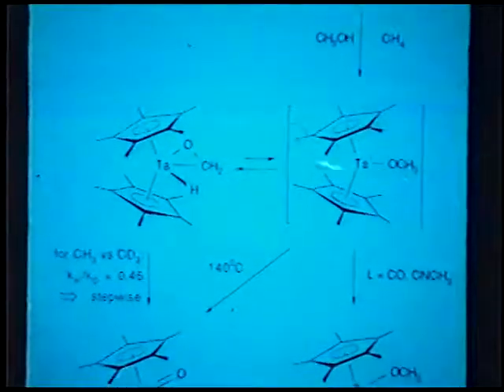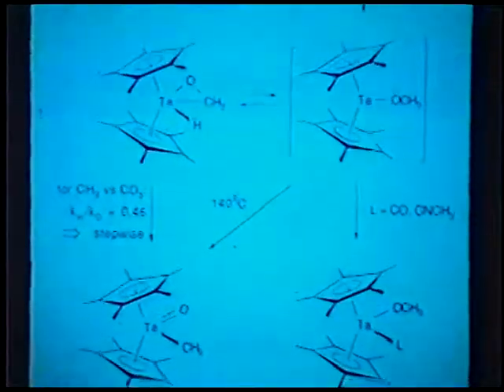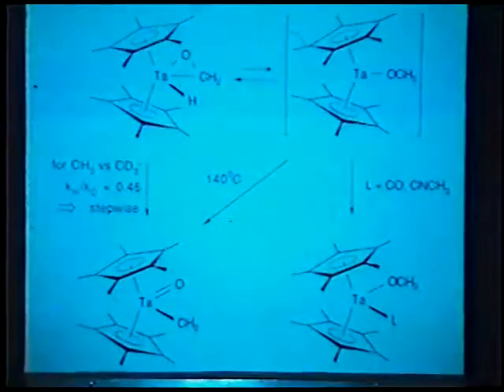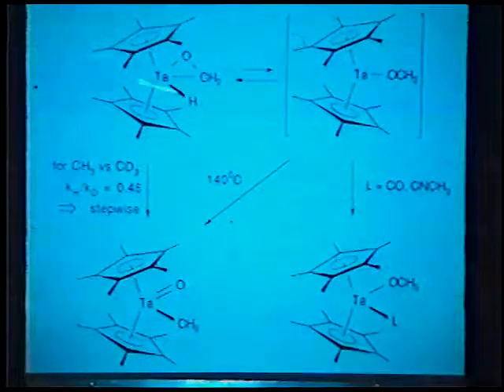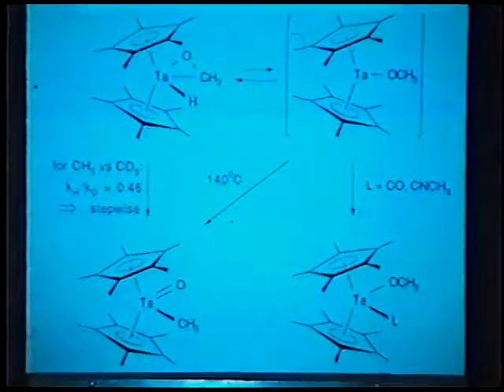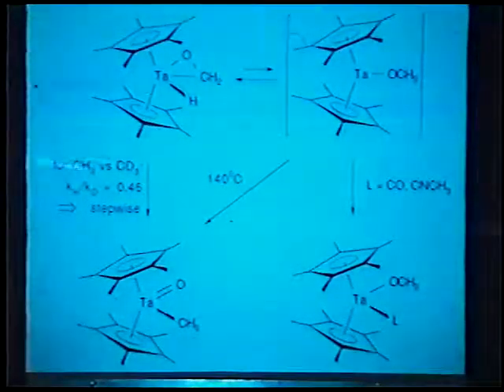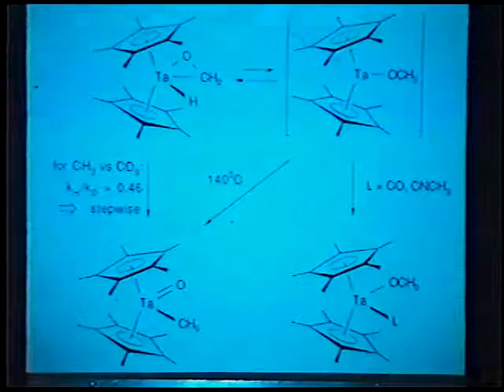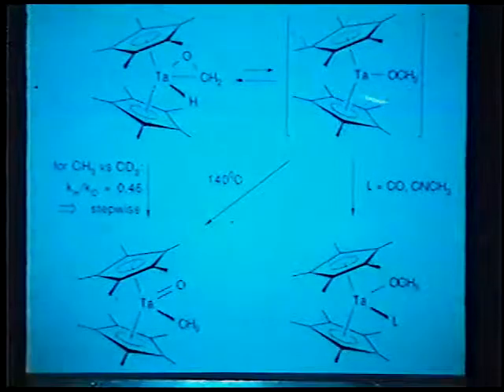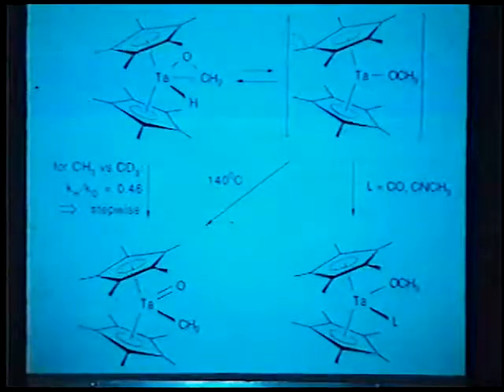With methanol, we get very clean transformations that involve loss of methane from the methylene hydride and formation initially of this formaldehyde hydride derivative of tantalum. This is reversible. You can show that by dynamic NMR techniques and also by trapping the methoxide with simple ligands like carbon monoxide or methyl isocyanide. Now, on heating, once these transformations occur, which involves carbon-oxygen bond cleavage, we give this oxo methyl group that I described a minute ago. Interestingly, when we substitute these three hydrogens with deuteriums, we see an inverse isotope effect, again, a signature of a stepwise process, almost certainly involving this hydrogen transfer that we know is going on, and then a rate-limiting carbon-oxygen bond cleavage. This is, of course, exactly the opposite of what I'd like to do. I'd like to do the microscopic reverse. And we're probably never going to do that with an early metal center like tantalum.